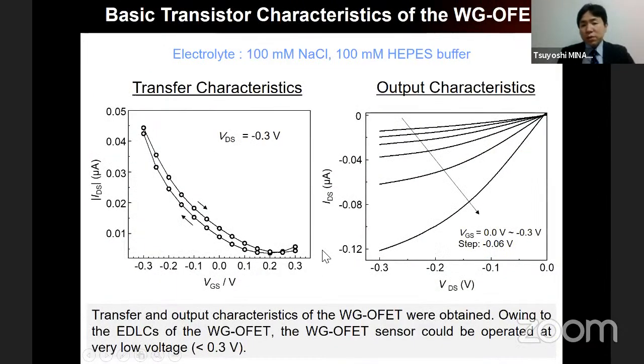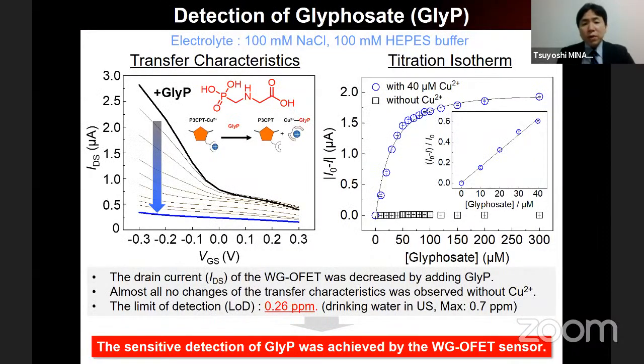Here are the transistor characteristics. With 0.3 volt operation voltage, we achieved a very low operation voltage, and there is almost no strong hysteresis, so we can use it for such sensing device applications. When we increase the glyphosate concentration, after the complex between the P3CPT and the copper ion, we observe a gradual change of the transfer property. In that case, we could clearly see the detection of glyphosate.